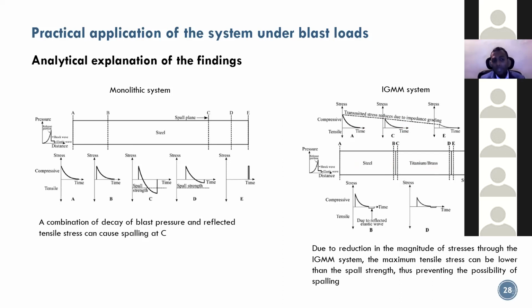So spalling is the critical failure in these cases. Spalling is effectively a tensile failure. So it's to do with the tensile stresses that get developed generally towards the back face, the face away from the blast. So what we are doing here is reducing the stress gradually through the system, so that by the time you get to the last material, our stresses have reduced significantly, to the extent that you will not get tensile failure.